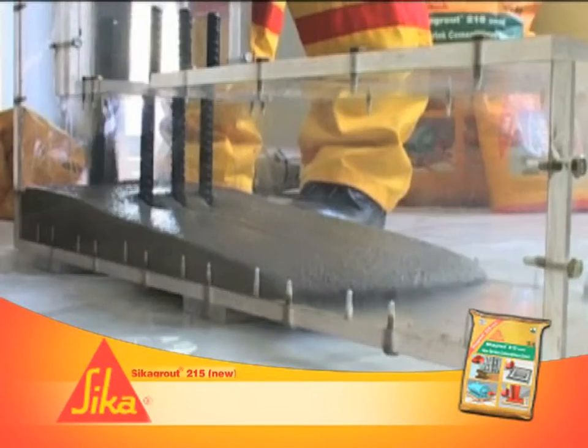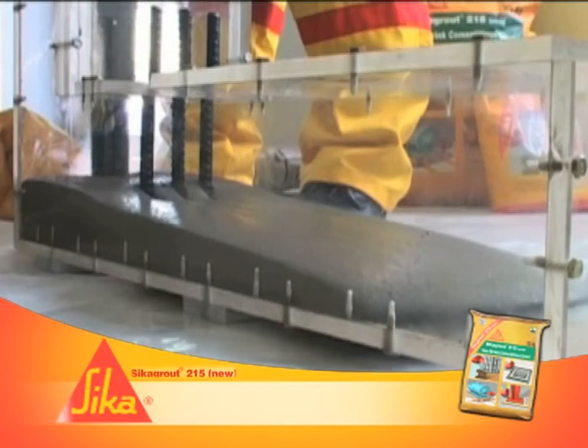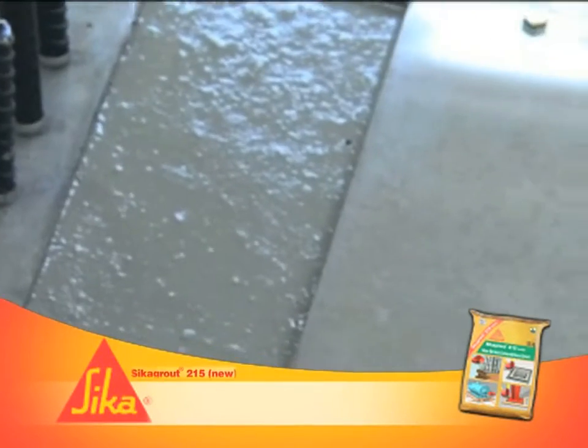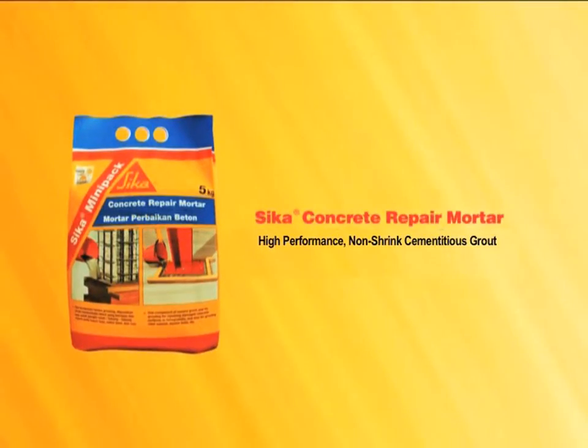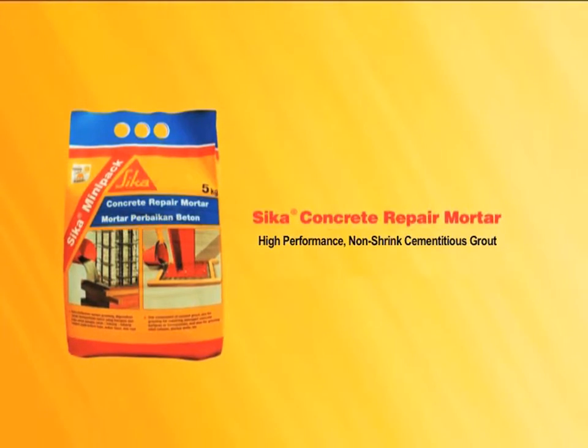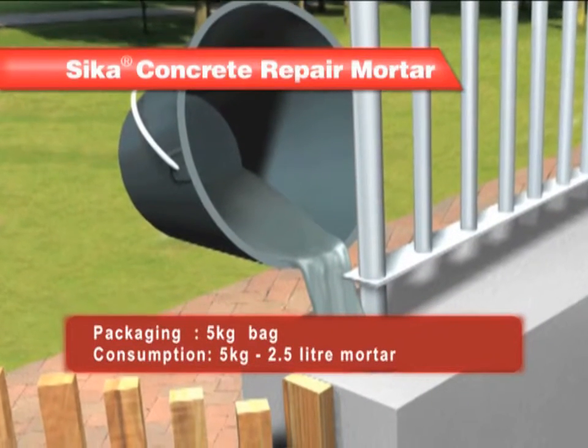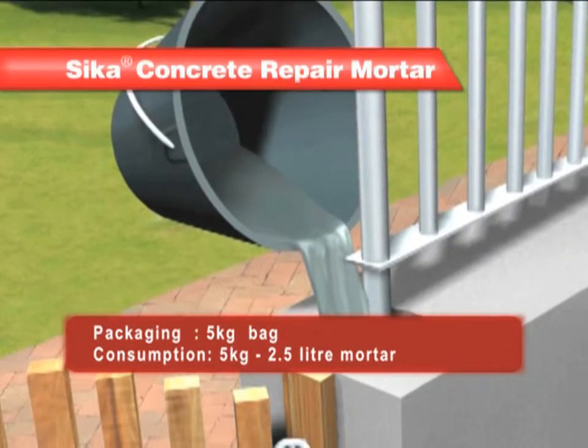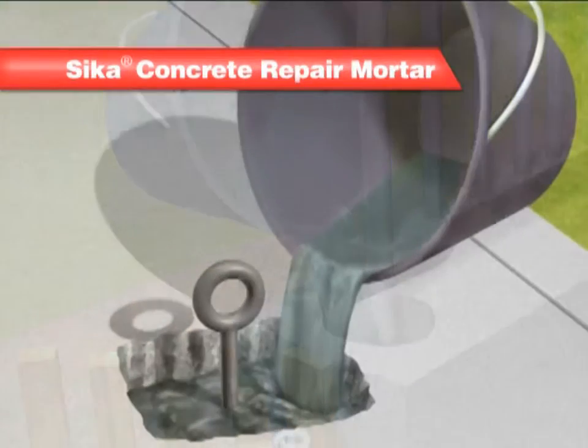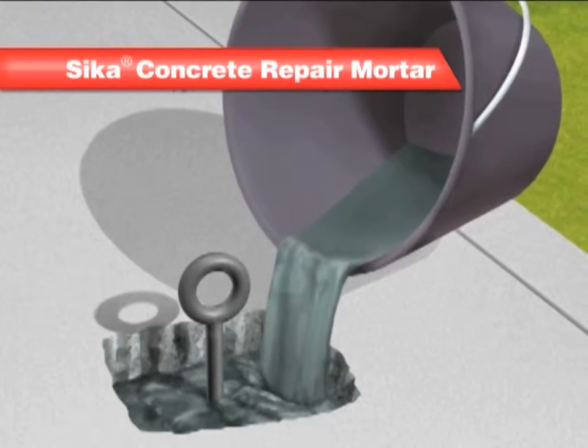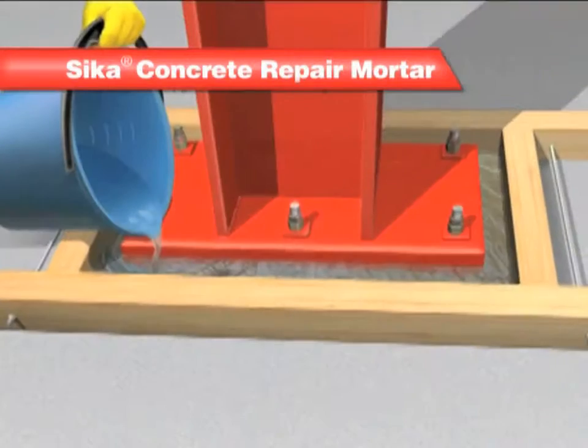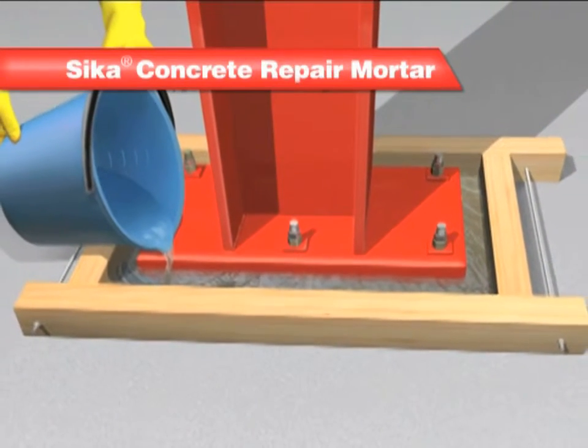Pour the mixture onto forms from one side so as to avoid air entrapment. Do not vibrate. Sika Concrete Repair Mortar. One component concrete repair mortar. Sika Concrete Repair Mortar is a ready-mixed cementitious mortar for concrete repairs, sealing of cavities or gaps, grouting, etc.